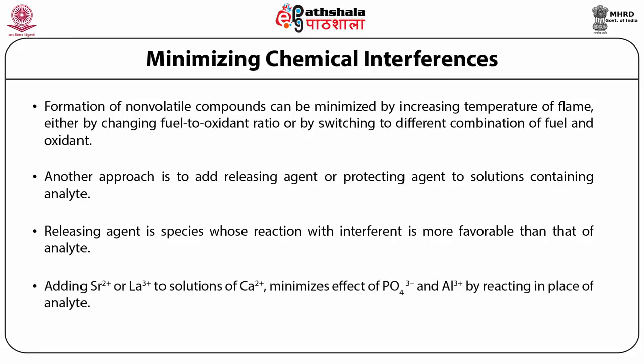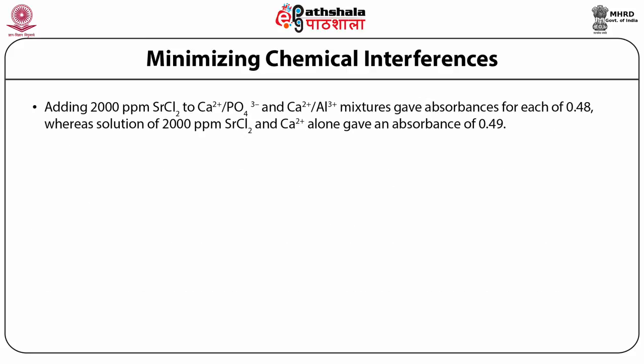Adding strontium ion or lanthanum to solutions of calcium ion, for example, minimizes the effect of phosphate ion and aluminium ion by reacting in place of the analyte. Adding 2000 ppm of strontium chloride to the calcium phosphate and calcium aluminate mixture discussed above gave absorbances for each of 0.48, whereas a solution of 2000 ppm strontium chloride and calcium ion alone gave an absorbance of 0.49.